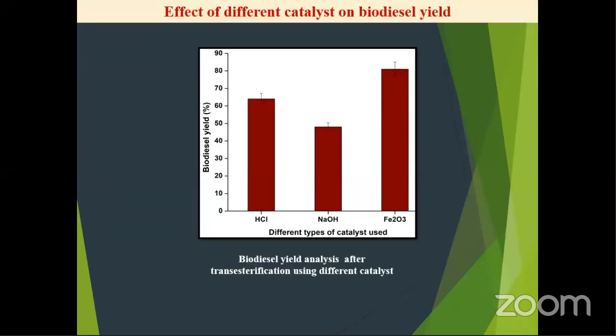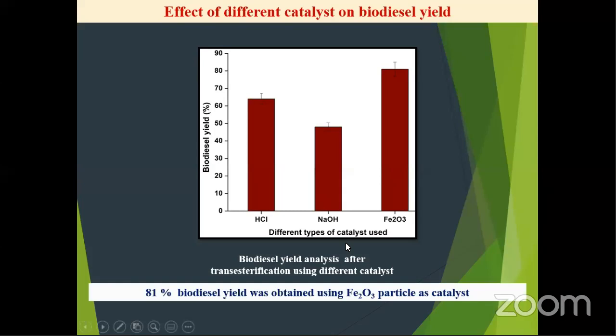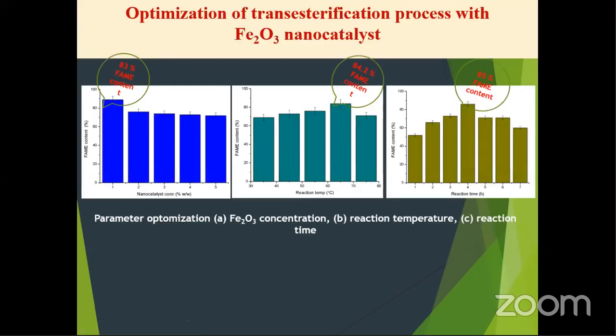And then the newly synthesized nanocatalyst was used in the transesterification process, and it was compared with the other conventional catalysts used in the transesterification process. And it was observed that 81% biodiesel was obtained using Fe2O3 nanoparticle, which is much higher than HCl and NaOH in the transesterification process. So after that